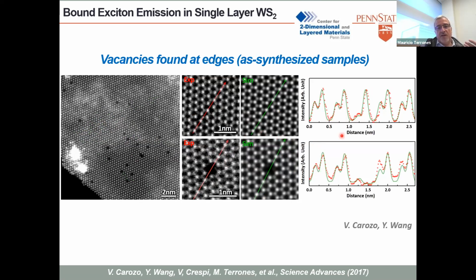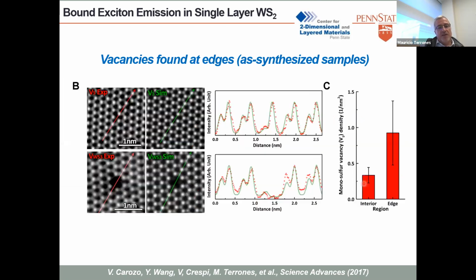You can see that this is a sulfur vacancy. This is when you have two sulfurs, one on top and one on the bottom. Remember the sandwich structure. But when one is gone, you have a reduction in the intensity, and then you have again one vacancy and then one metal vacancy as well. So we did the estimation of how many vacancies there are on the outside, at the edge, and in the interior,